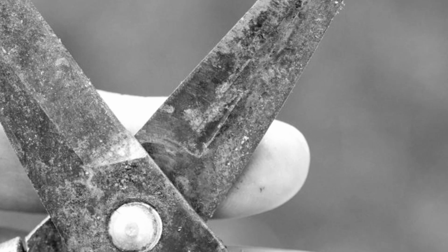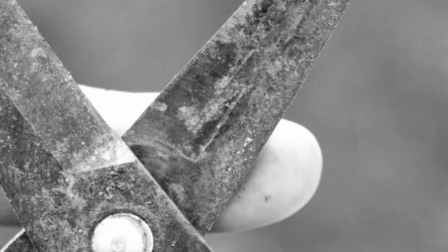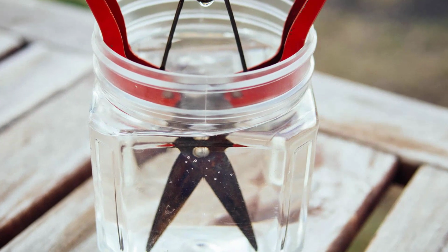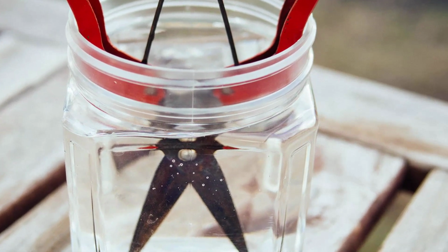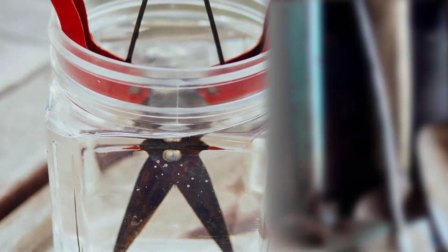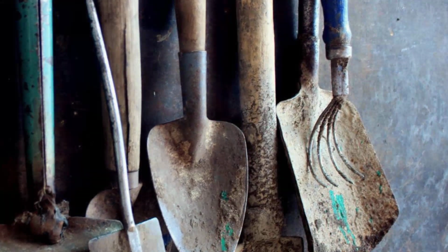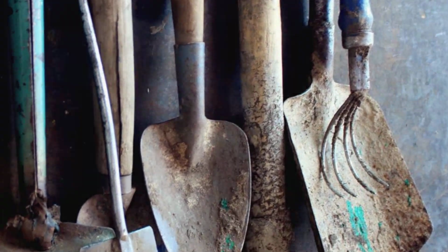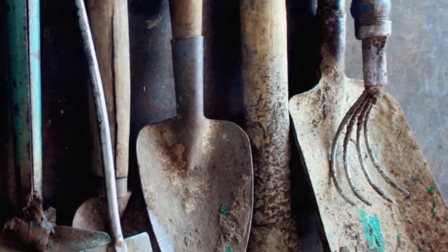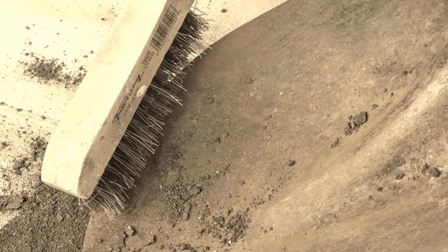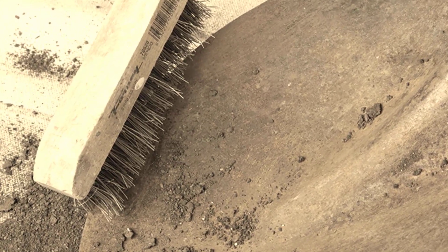Rust is a compound, not a coating. Mild acid dissolves iron oxide readily, breaking it apart and taking it into solution. It attacks bare steel too, but very much more slowly, so there is a wide window where the oxide is being stripped and the metal underneath is essentially untouched. This is the entire difference between chemistry and abrasion.